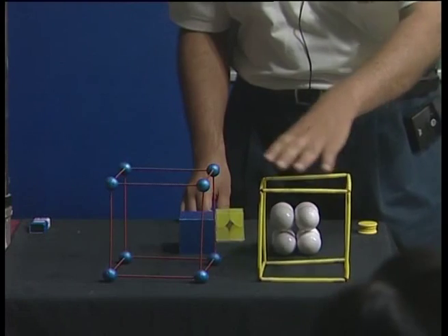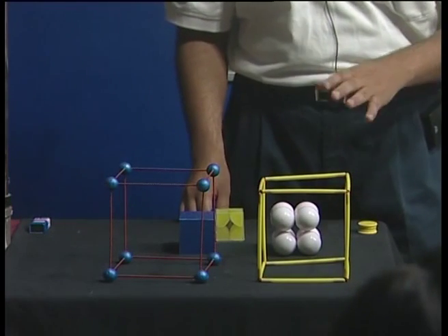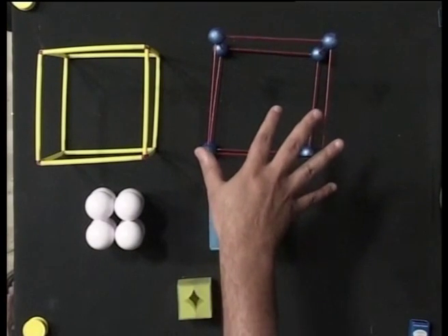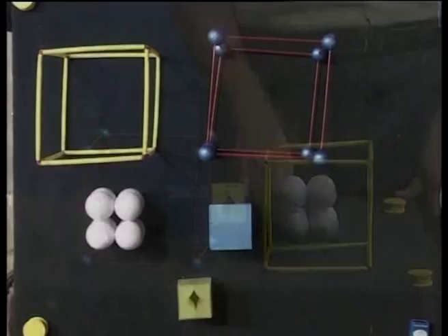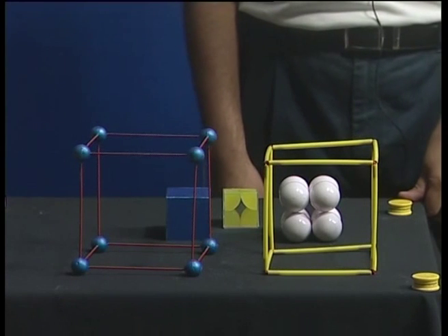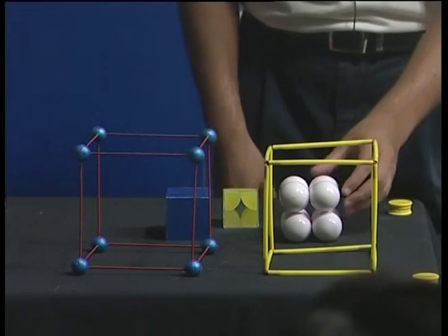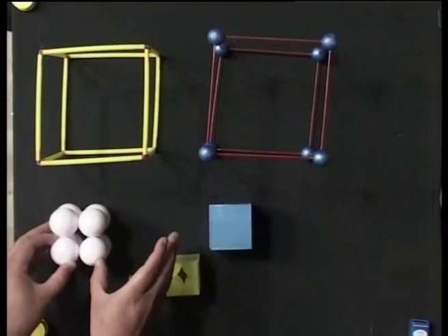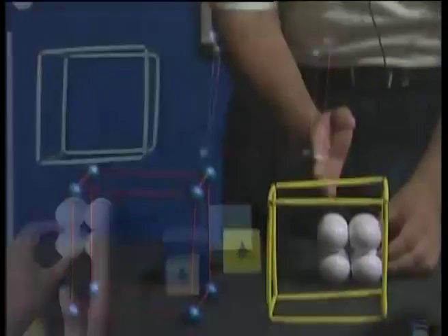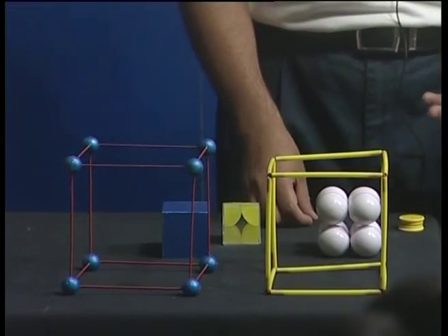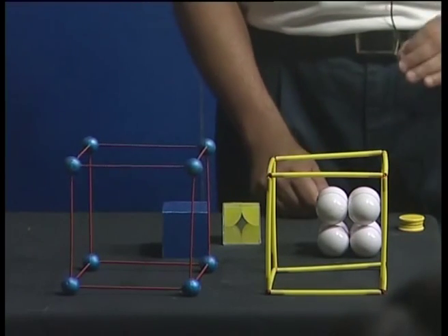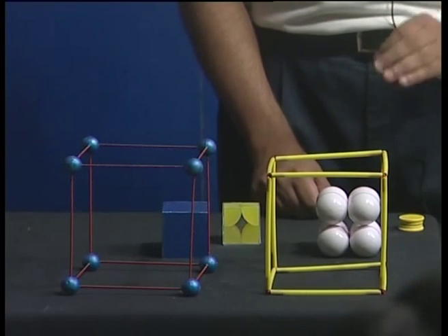That means I can put these kind of unit cells together in 3 directions to get a space filling. Now, technically speaking, I cannot do space filling with these 2, and therefore I need to consider another kind of model, which you can see here, which is truly a space filling model. In other words, if I were to put an identical unit cell of this to the right hand side, these white units with these white balls, then you can see that half of the atoms will overlap. That is not allowed. Therefore, both of these cannot qualify as the unit cells of the simple cubic crystal.